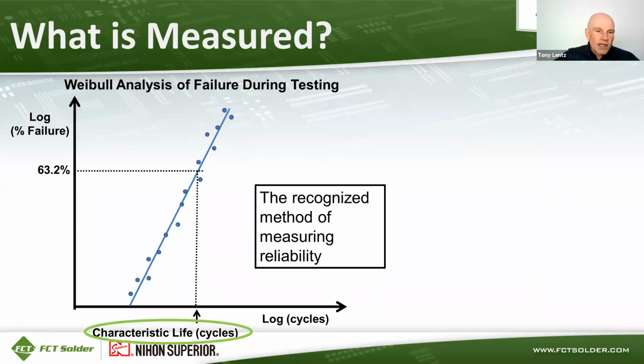Typically, reliability data is presented in a plot like this. This is called a Weibull analysis of failure rate. So the log of the failure rate is shown on the y-axis typically, and then on the x-axis we have the characteristic life, or the number of thermal cycles that the assembly reached. And then we would look at the 63% failure rate, and then that could be used as a characteristic life for the number of cycles that assembly lasted in that test method. This is pretty well recognized in our industry and is fairly common.